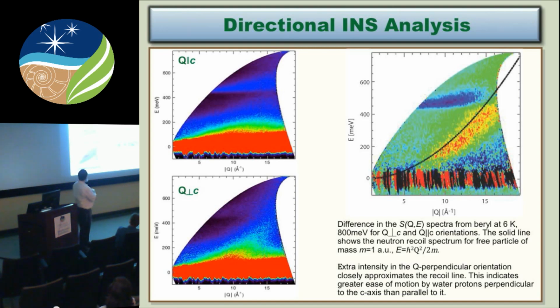Dave Wasowski calls these things shark fin diagrams. He doesn't like them very much, but actually it's a very useful way to see things because you can see both energy and space at the same time. So what you're seeing here is two INS spectra, one taken parallel to C and one taken perpendicular to C. And then we can take the difference and see what's happening. You see a couple things in here. First, you see this pattern right here. See all the yellow? The solid line is the recoil spectrum from a hydrogen atom. So it's just free particle recoil. And what you see is this significant intensity here in the Q perpendicular orientation.